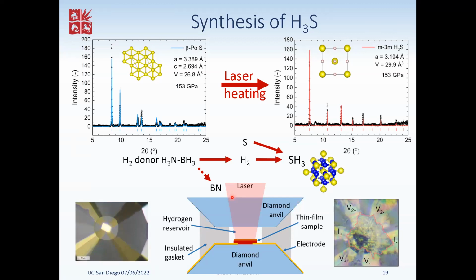What we rather use is a hydrogen donor material, ammonia borane. This is the chemical formula, H3NBH3. You can see it contains a lot of hydrogen. In fact, the hydrogen density of this is comparable, or actually equal, to pre-compressed hydrogen or to liquid hydrogen at cryogenic temperatures. So we've got no disadvantage in terms of the hydrogen that's available there. Does it lead to contamination with nitrogen? It does. I'll point that out.